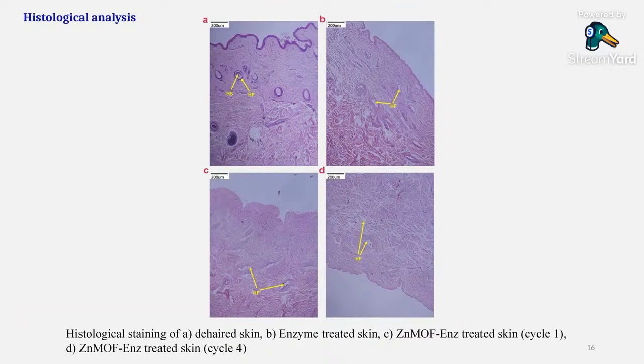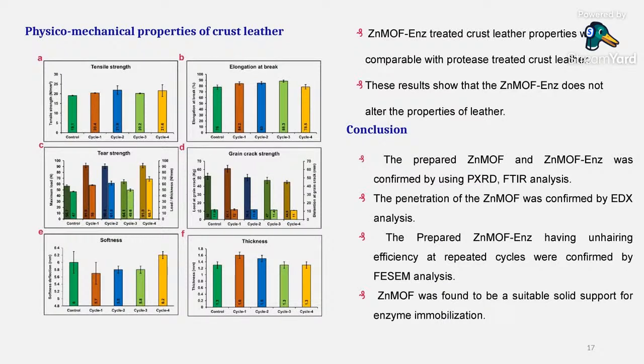The next thing is we looked at the histological stain of dehaired skin, enzyme treated, and ZnMOF-Enz treated, and everything is going perfectly well. There was no problem on the skin. Whenever people do the unhairing process, they want to go on to chrome tanning and see how this enzymatic process gives better stability, mechanical strength, tensile strength, grain crack strength, thickness, softness, everything, because there will always be some changes when you use the sodium sulfide based unhairing process or the enzymatic unhairing process. So we want to make sure everything is compatible and matching with what is commercially available.